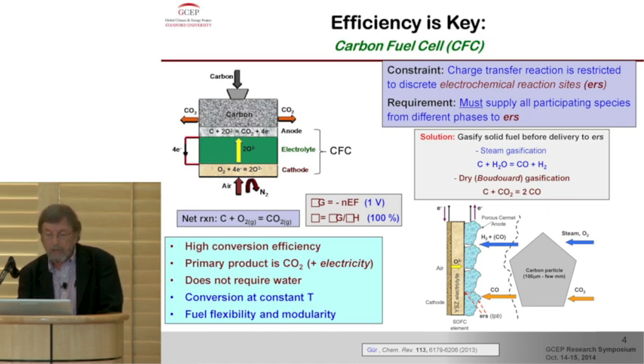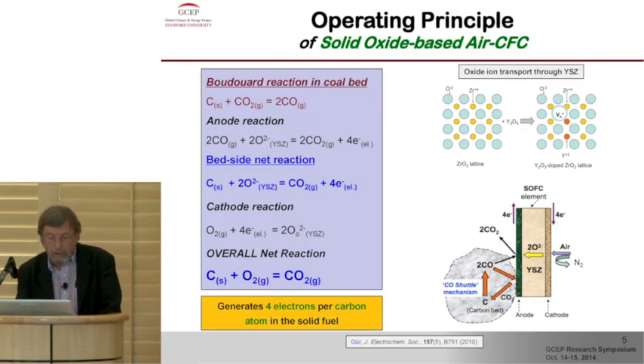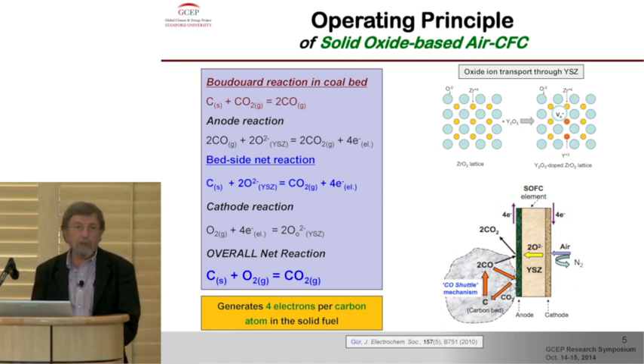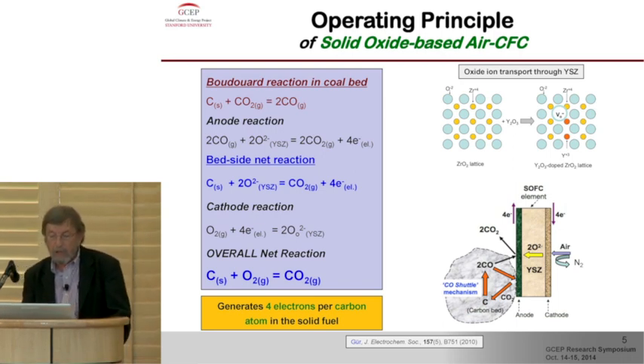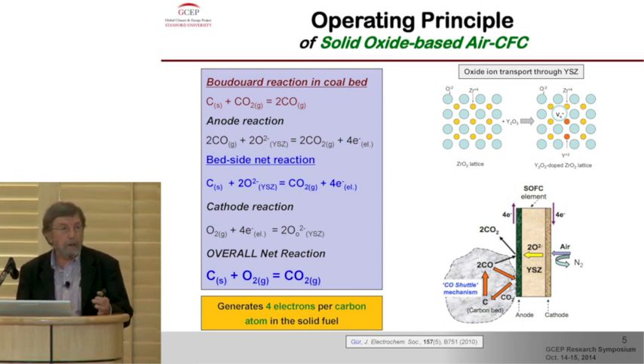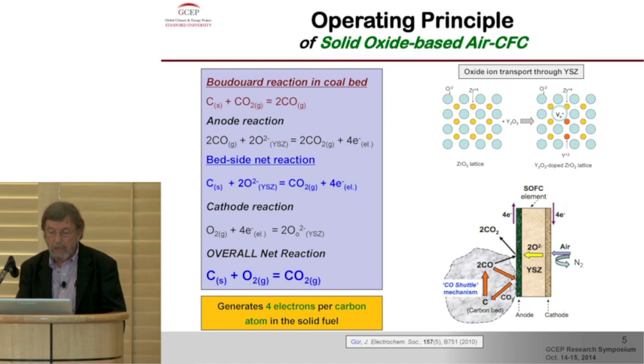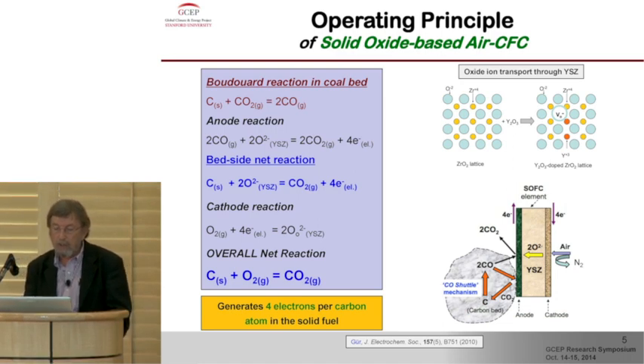And the CO is oxidized at the electrochemical interface. So that's what happens. The CO that is formed here is oxidized by the oxygen that's coming through. We have a ceramic electrolyte, yttrium-stabilized zirconia, which is commonly used in solid oxide fuel cells, and it transports oxide ions through the vacancy mechanism. The vacancies are formed by extrinsic doping to maintain charge neutrality in the oxide.